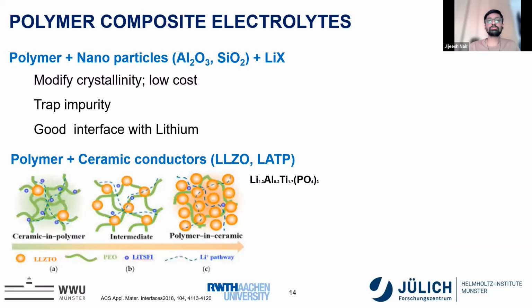Then there is polymer composite electrolyte. For example, in the beginning, in the 80s and 90s, there were attempts to increase the mechanical properties and increase the amorphous nature of the polymer by adding nanoparticles, either alumina, silicon dioxide, etc., with the lithium salt. These are cheap and they can reduce the crystallinity and trap the impurity, and this can also form a better interface with the lithium, so the lithium interface can resist the dendrite.